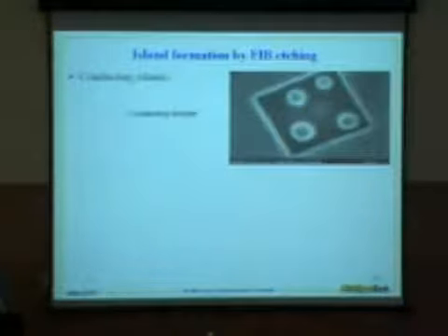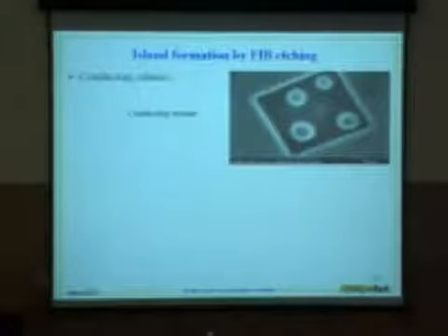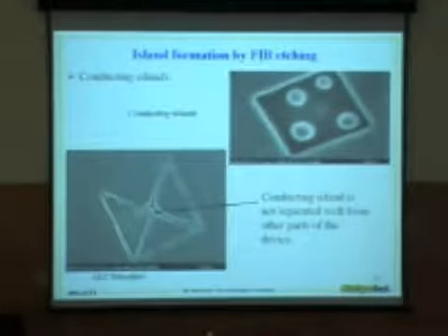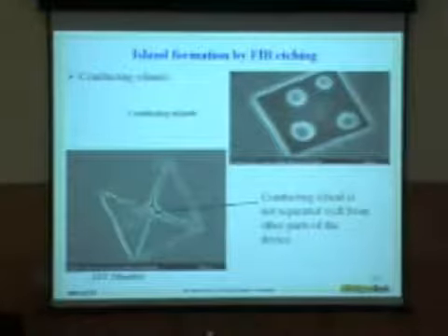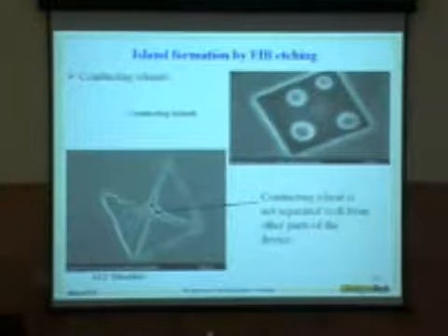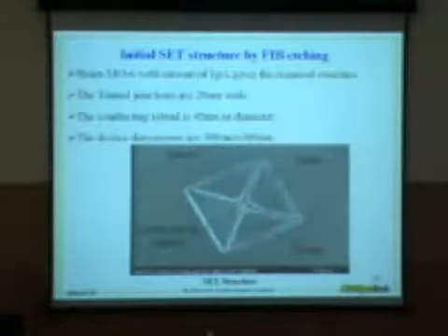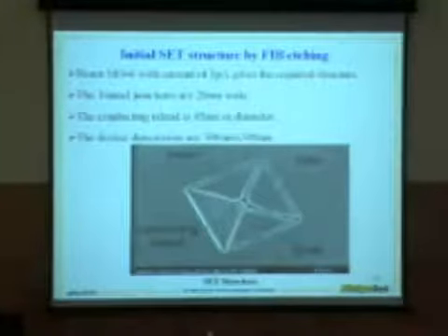The effort has been used to initially look at what kind of minimum features we can produce. These were some features that were down in the 100 nanometer range for etching. We wanted to see, can we produce quantum dots by this method out of a continuous sheet of metal. And we've shown that yes, you can, but in the etch method you're limited in the production of the dots based on the size. We found this somewhat troubling because we didn't really want a SET with a 40 nanometer quantum dot. We wanted an SET with a quantum dot that was significantly smaller, so that it would be much more feasible to operate at room temperature. A 40 nanometer dot basically can operate in the liquid nitrogen temperature range.